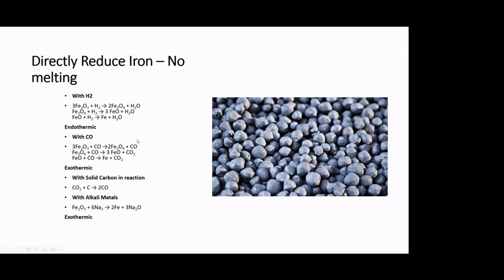You could use carbon monoxide, and that's what is used with natural gas and other processes. That's an exothermic reaction, so you just have to have enough heat for it to start, and it'll generate its own heat. Solid carbon, which is sort of like what happens with New Zealand Steel's processes, and the Helios process using alkali metal, is again an exothermic reaction. So you only have to heat it up to a few hundred degrees and the reaction takes care of itself.